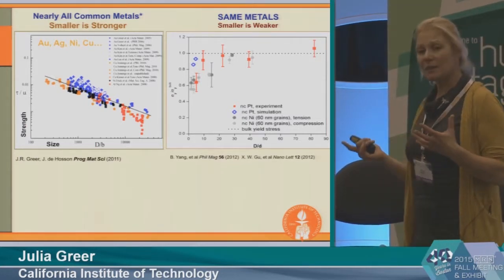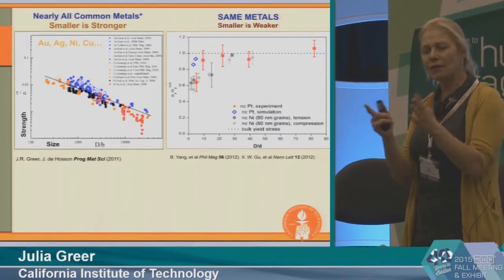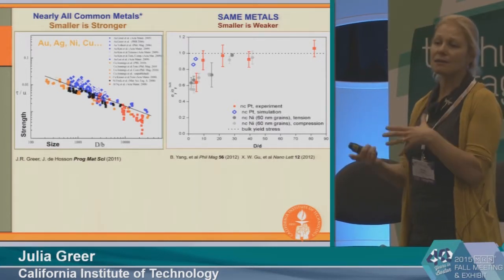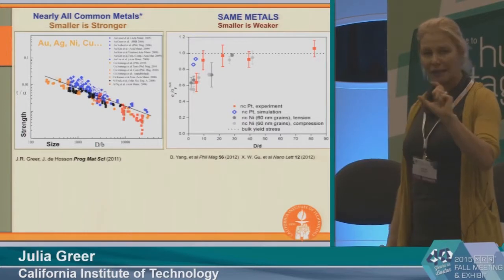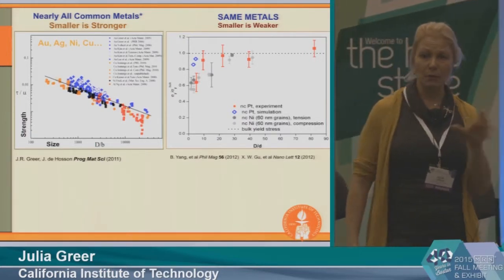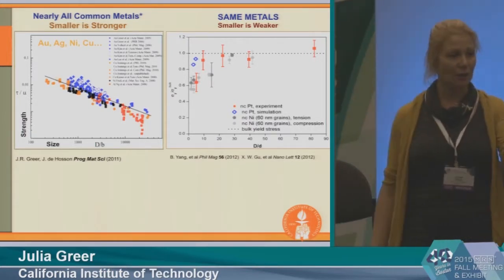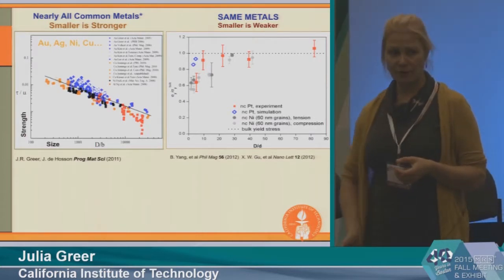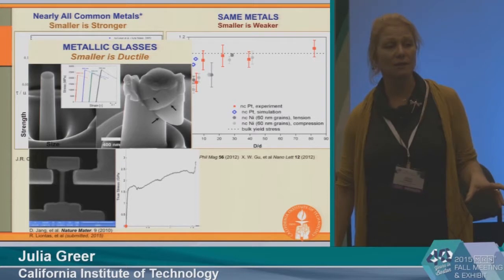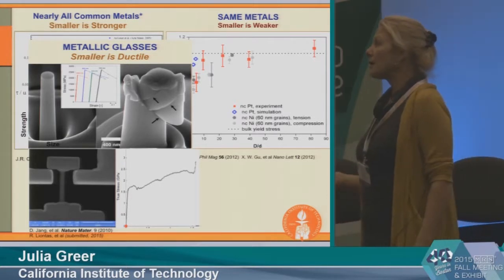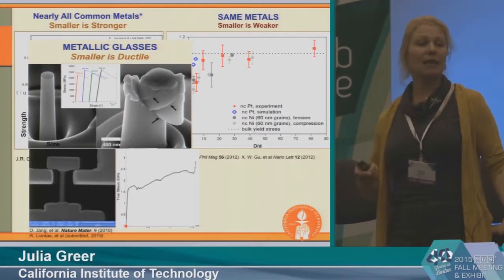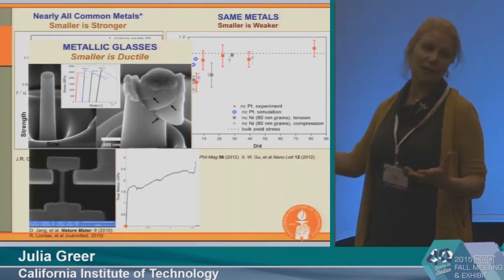So what you're learning from this is that, wait a minute, if I know both the nanometer size dimensions and the atomic level microstructure, both of those are tuning knobs for strength, so I can really control and tune my strength. But what's even more powerful is that the size effects don't manifest themselves only in strength. In fact, materials that are intrinsically brittle, like glasses, and I'm choosing metallic glass as an example here.